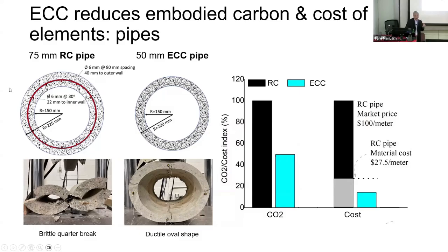So in order to achieve this, it is important to think of ECC as a material that should be used with proper design of the structure. You don't want to replace conventional concrete with ECC one-to-one and not make any changes. If you do that, then it typically raises the carbon footprint and it raises the cost. So this is an example where I want to emphasize that you really need good structural engineers to appreciate how the material behaves and use that in the design process to reduce the amount of material, and you typically carry that out by modifying the geometry, and possibly removing steel reinforcement.